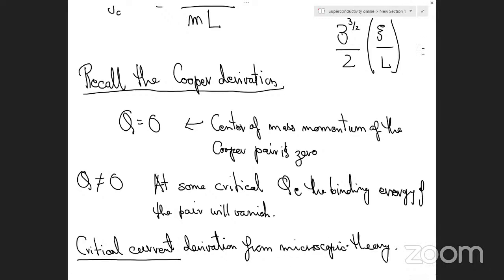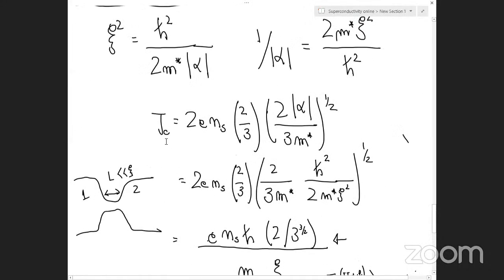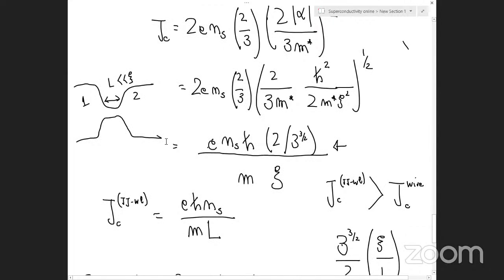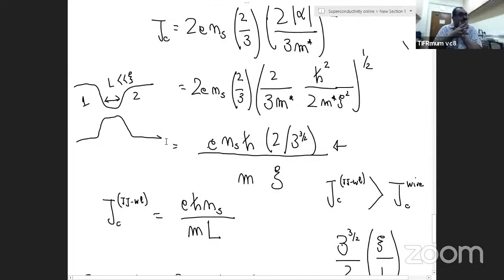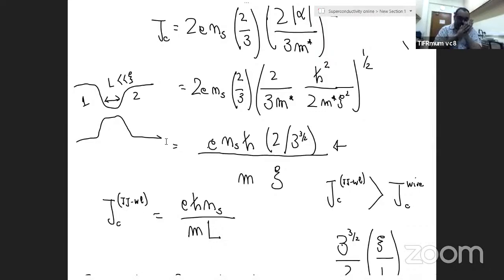Sir, it's something about the assignment, in the second question, that at low temperature the Ginzburg-Landau coherence length becomes the BCS coherence length. Yes. But I'm not getting the factor exactly equal to 1. It's like 0.9 or something. Yeah, that's right. There's nothing wrong. Look, the problem is that the BCS coherence length, if you do the various kinds of derivation, you have already seen that there is always a factor of the order of unity which is slightly different.